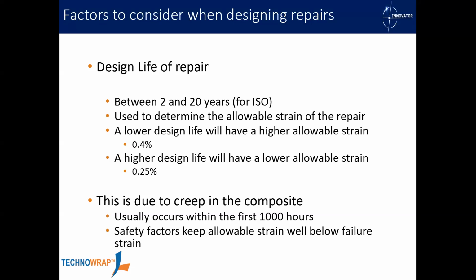And then leading on to the design life of the repair. So for the ISO standard, this sets the figure between 2 and 20 years. For PCC2, again, as Shona mentioned, it gives you a range between short-term and long-term. However, what the range actually indicates is a short-term condition is 2 years and a long-term condition is 20 years as per the ISO standard. So both of them are very closely tied. But what that does mean is, for the PCC2 standard, you can actually extend the design life out, as long as the design conditions allow. You can extend it further than 20 years if required.